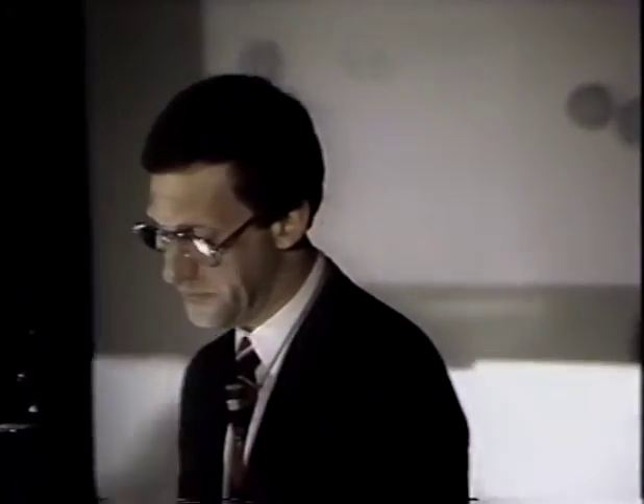At that time, we proposed an orthorhombic cell a long time ago, 2 weeks ago actually. And in the meantime, single crystal X-ray diffraction work by Siegrist and Sunshine has confirmed this original projection. And that's the structure, that's one unit cell. It appears rather dark. I apologize for that.